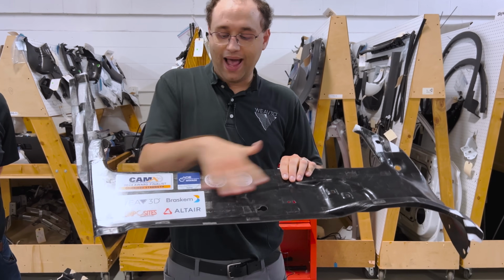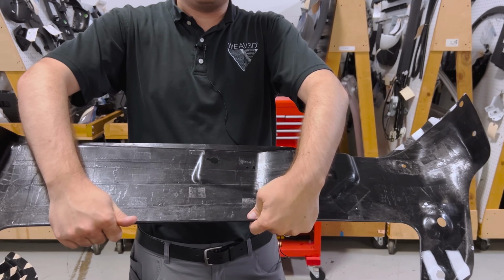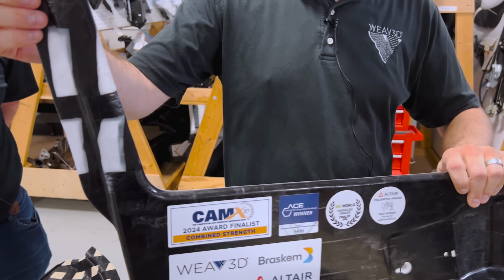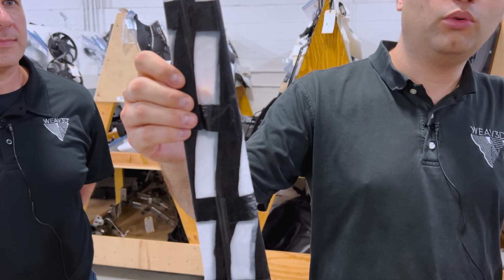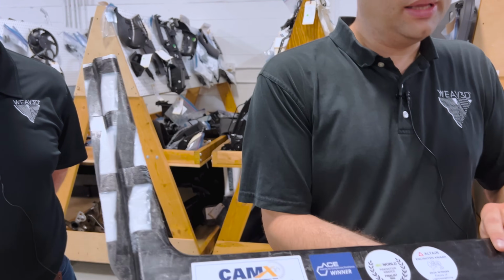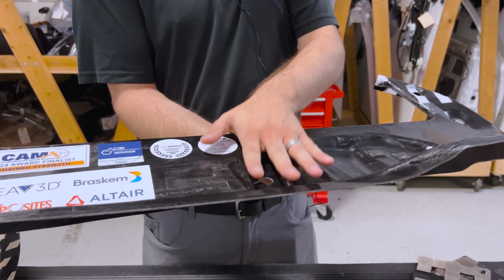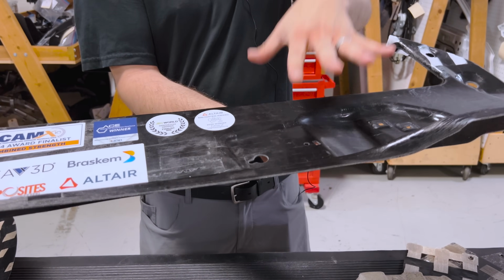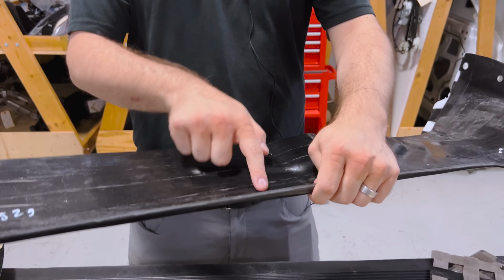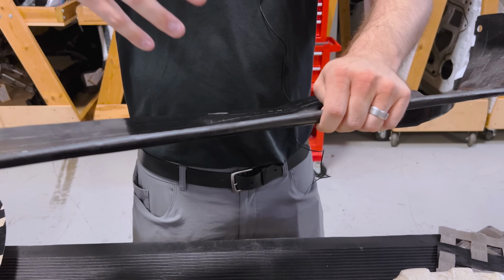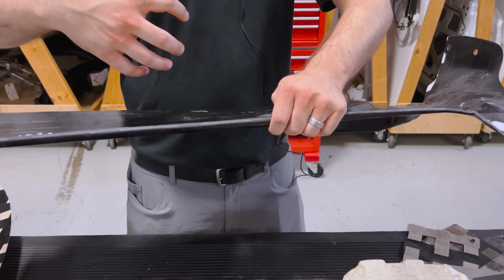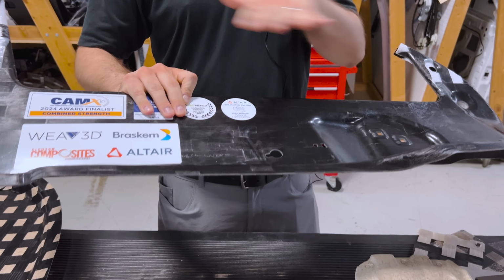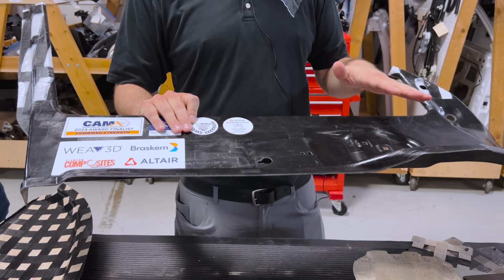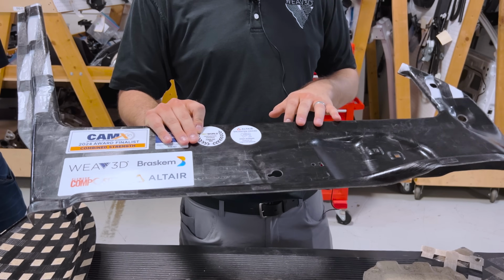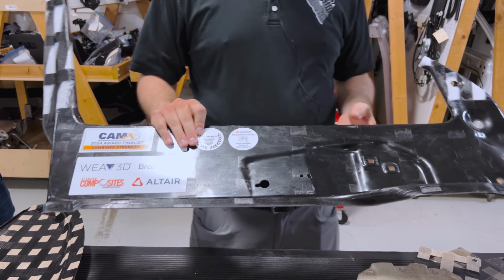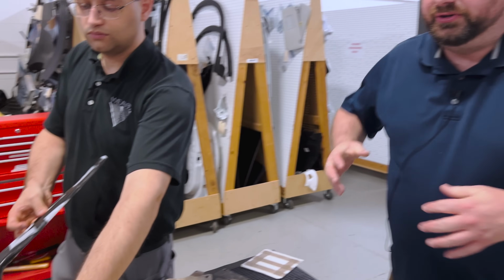So you have this lattice on the top and bottom sides of this part, and inside the middle of the part you have this polypropylene sheet. This is an unreinforced polypropylene. And what we see when this part actually gets loaded for a side pole crash type test is the part flexes and we crack the fibers on the backside, but then the part continues flexing because the polypropylene is still fine. So then when you take the load off, this actually rebounds back to its original shape as if there was no damage to the part at all, except for the small amount of surface cracking you see in the fibers.